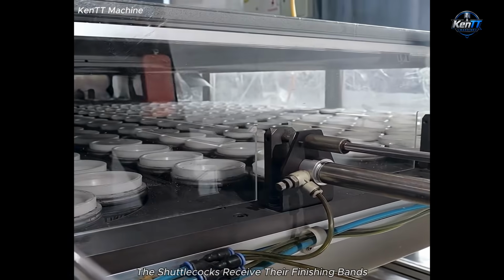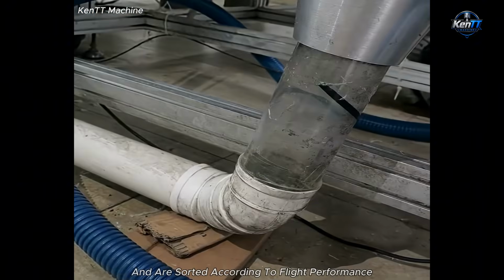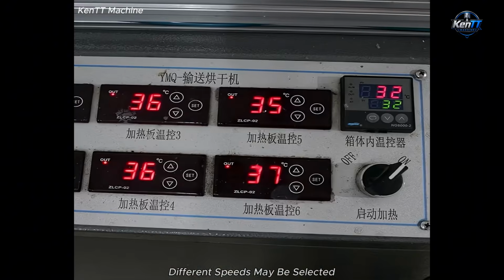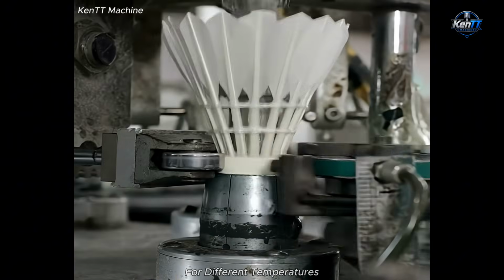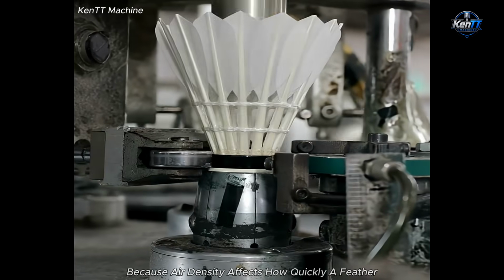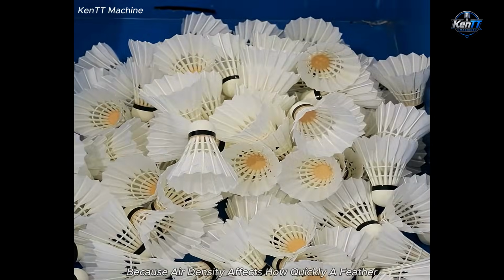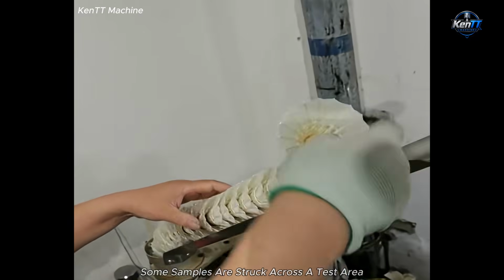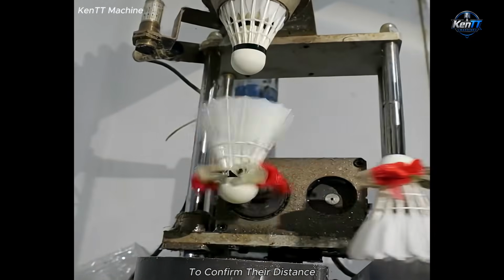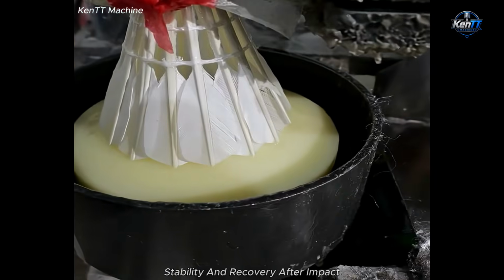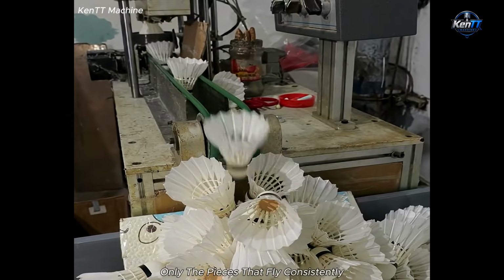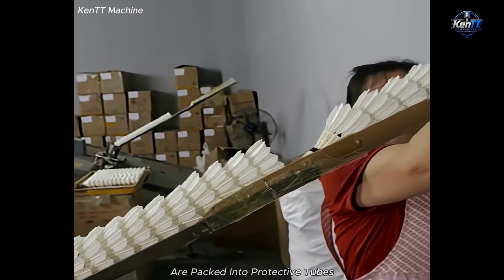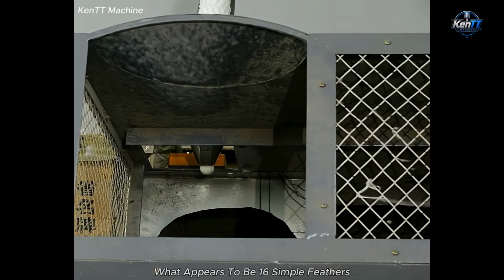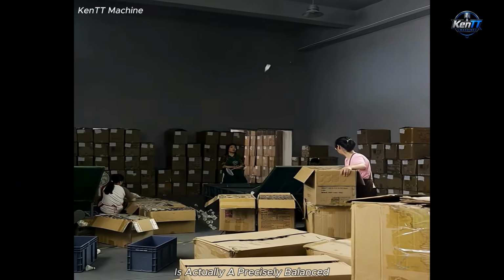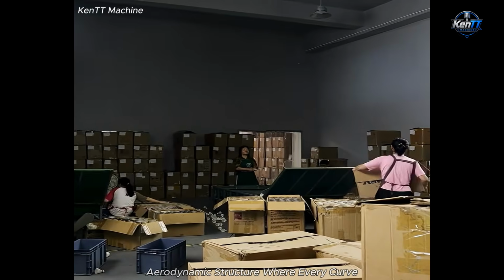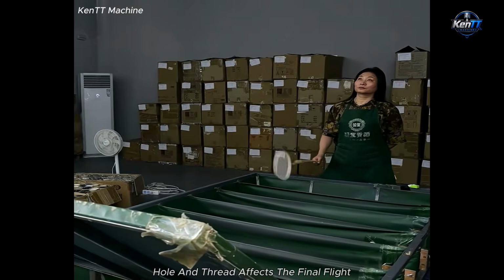The shuttlecocks receive their finishing bands and are sorted according to flight performance. Different speeds may be selected for different temperatures and playing environments because air density affects how quickly a feather shuttlecock travels. Some samples are struck across a test area to confirm their distance, stability, and recovery after impact. Only the pieces that fly consistently are packed into protected tubes. What appears to be 16 simple feathers is actually a precisely balanced aerodynamic structure, where every curve, hole, and thread affects the final flight.